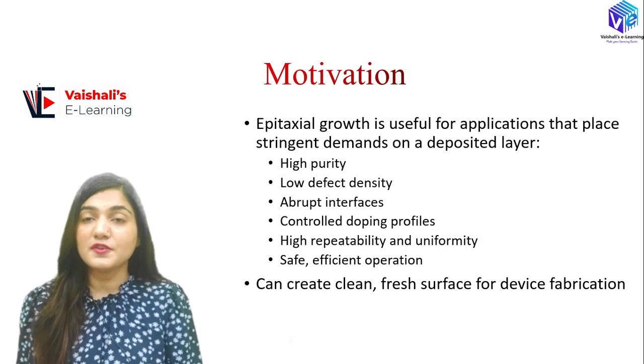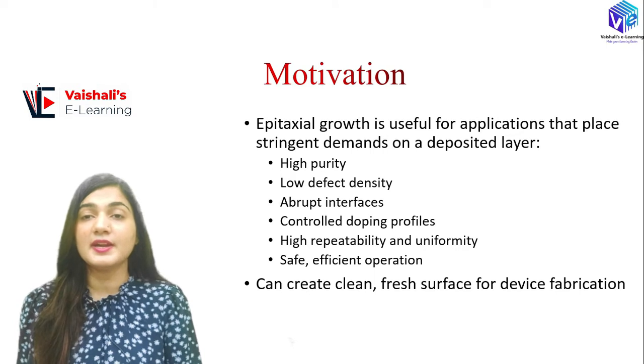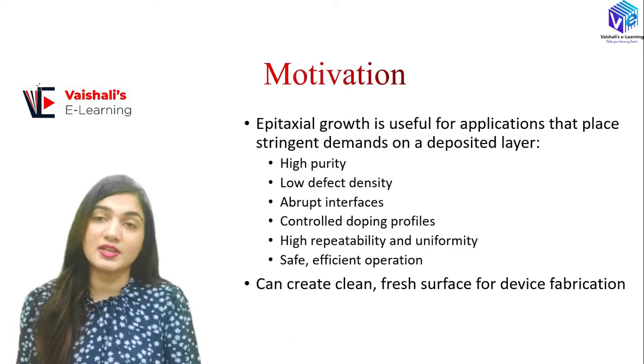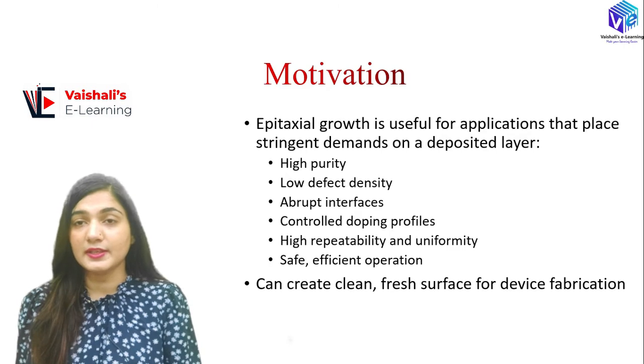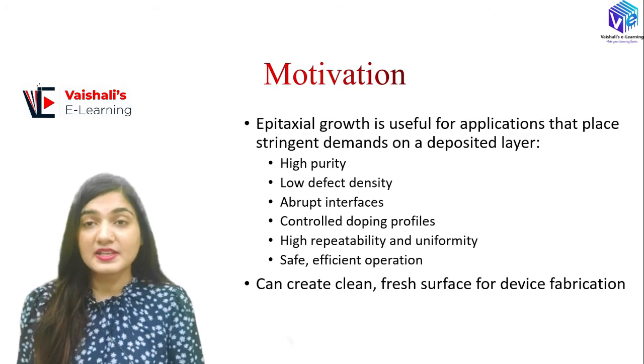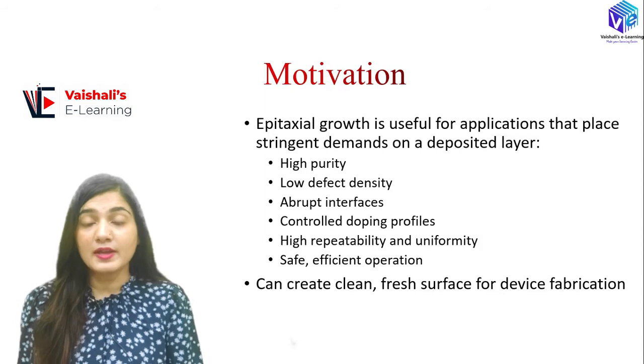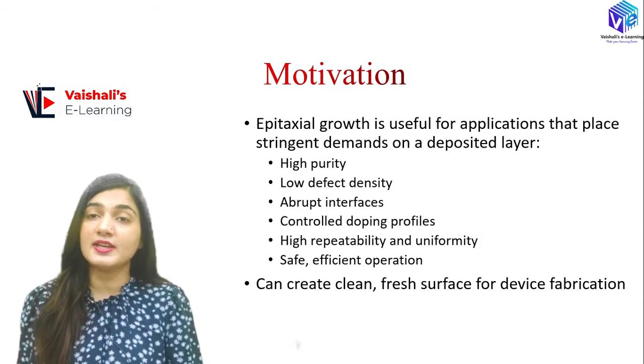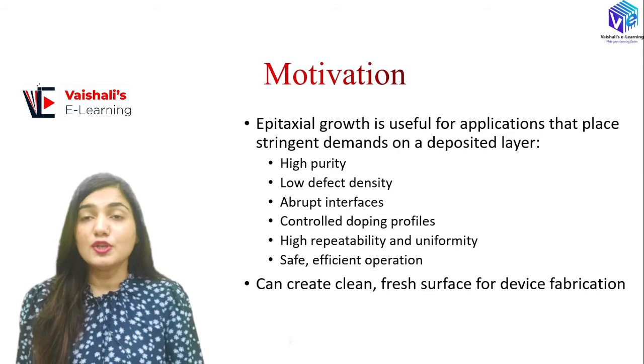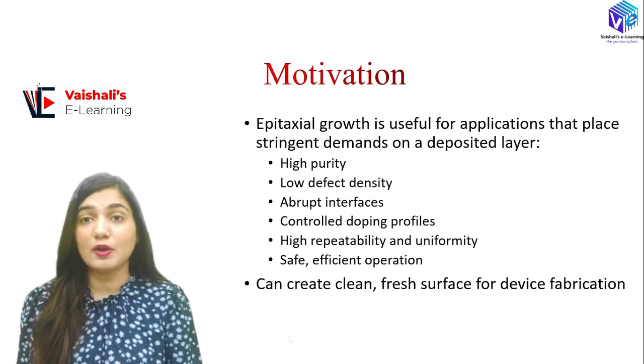When we process a wafer, because the wafer is mostly made using a quartz crucible, impurities like carbon, nitrogen, and oxygen are very common in the wafer. However, on the substrate we can create a highly pure epitaxial layer, which is called the epitaxial layer. The purity is very high.